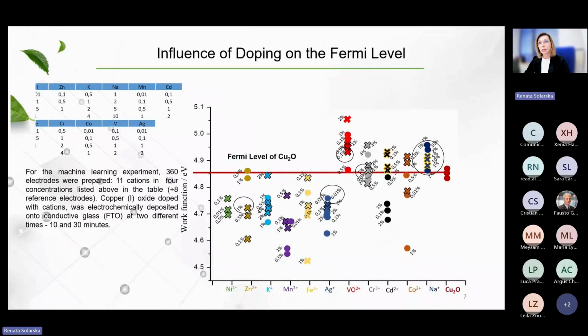And so, as I said, it's clear that we need a hybrid system where the weakness of the material can be compensated by the second phase, or we can take advantage by keeping the electronic structure of the copper oxide in the bulk and improving the kinetics of the surface, or by adding a co-catalyst with good absorption energy towards copper 1 oxide.